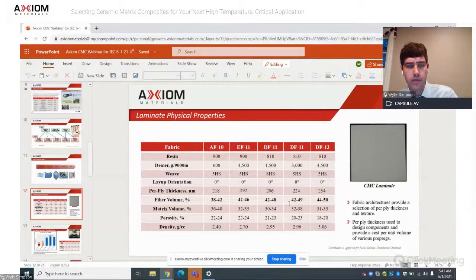Fiber volume for this stuff is typically around 42 to 50%. Matrix volume around 30, and porosity, you're going to see a porosity of around 20%. Now that porosity is essential in a system like this ox-ox system, because it allows those sort of weak fiber matrix bonds to form, which are essential in deflecting and impeding crack growth through the system. So that's why 20% porosity is sort of inherent to the system and necessary for it not to become brittle.